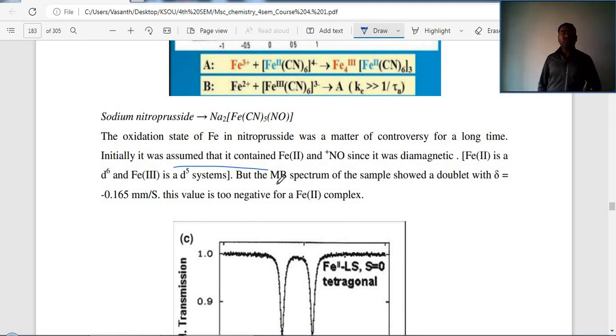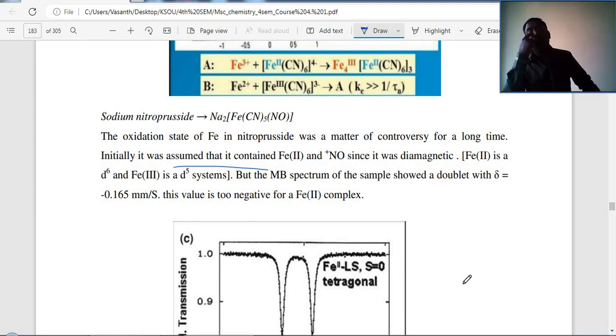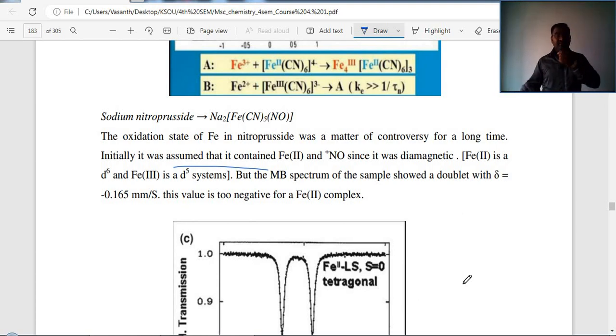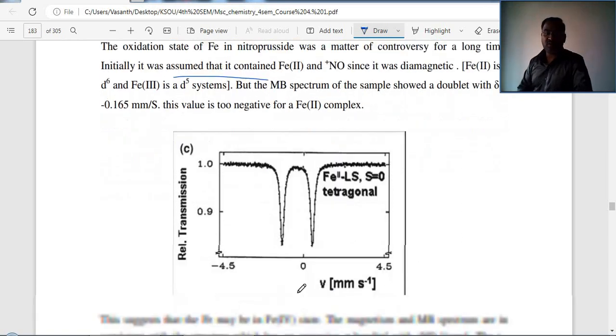Initially it was assumed that it contained Fe2 plus and NO, since it was diamagnetic. But the Mossbauer spectrum of the sample showed a doublet with an isomer shift value that is negative, unlike an iron 2 complex.